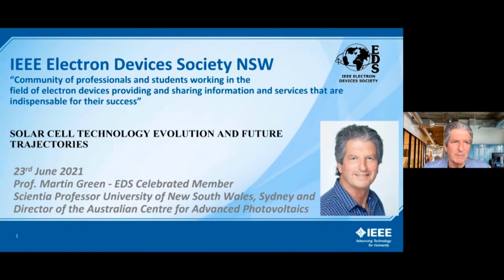And I think they're already talking about 130 micron wafers. And the IBC, the interdigitated back contact technology, is already using wafers around 130 microns. So there are already thinner wafers being used in the industry, but not for the mainstream. It turns out that the wafer cost isn't the most important issue, and it's better to remove the extra challenges associated with thinner wafers in terms of increased breakage rates and things like that. It's better not to have to solve those. It's better to pay the extra for a slightly thicker wafer than to have to address lower yields from the thinner wafers that you'd see as a consequence. So yeah, I think the industry will steadily move to thinner wafers, although at the moment it's not a number one priority.